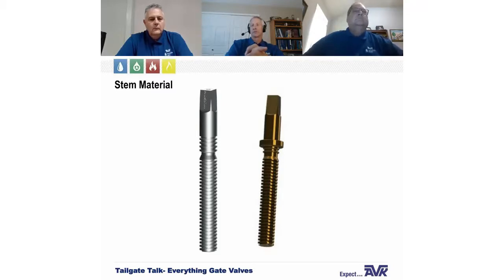We do this because some of those applications can be a low oxygen environment. And for stainless steel to remain corrosion resistant, it has to have oxygen to create that chromium oxide layer on the exterior of the stainless steel. For low oxygen environments, brackish environments, high salt environments, the low zinc bronze stem is what we recommend for that, which is better or superior to 316 and 304 as well for those applications.